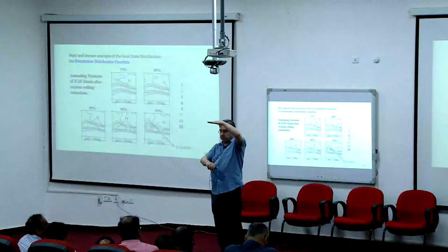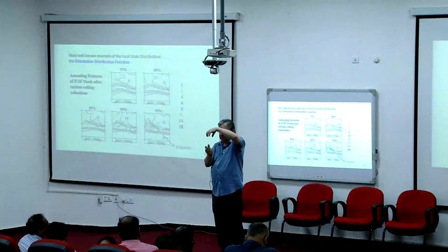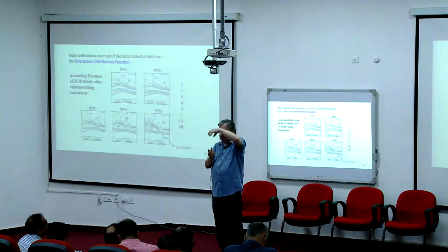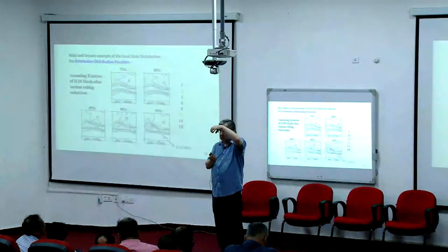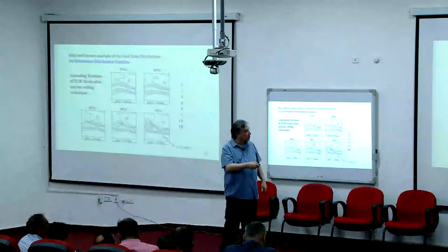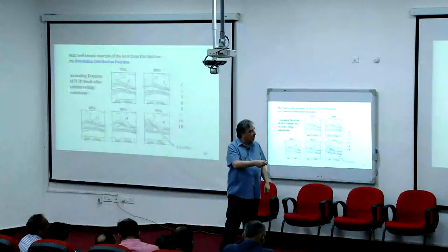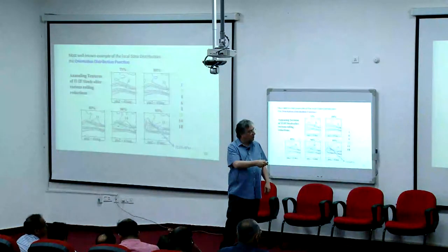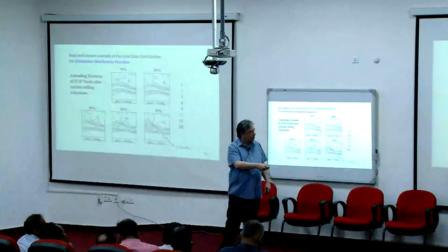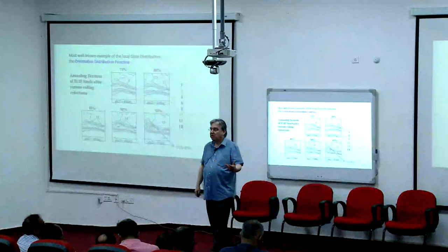that you can make cups with a high limiting drawing ratio, this is called, but also that you don't have ears. And actually, the earring behavior scales with the intensity distribution along this fiber. Like you can see, this is very good. This is much worse because here you have a maximum. So if you deep draw this steel, you will have a strong earring behavior. If you deep draw this steel, you will have close to no earring behavior.